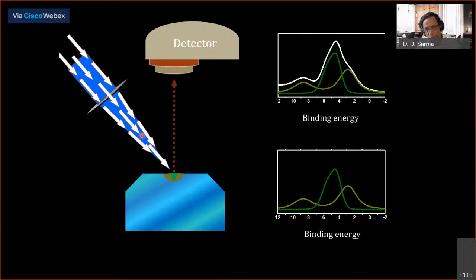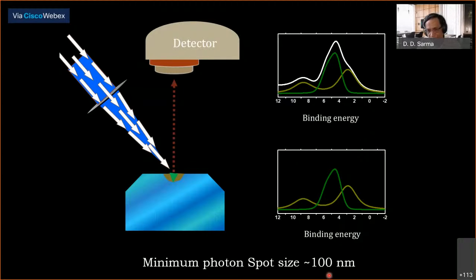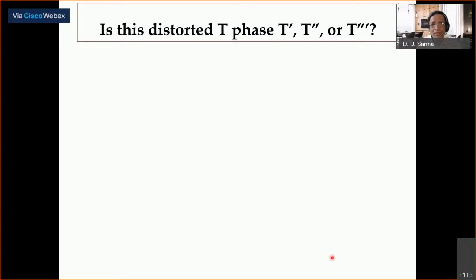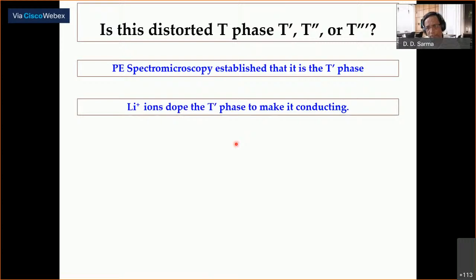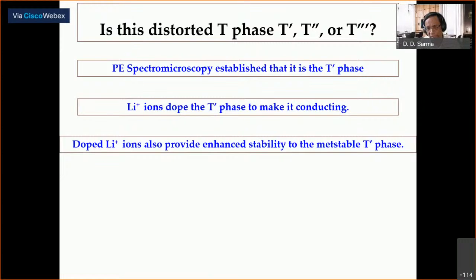You have a lateral resolution because you're focusing the photon, and the photon can be focused. It is one of the best beamlines in the world that we worked on at Elettra. It's 100 nanometers width. And so we figured out that it is actually the T prime phase. We've shown why the system becomes conducting, and that also the lithium doping can make it stable. But that is not what I'm going to talk about.